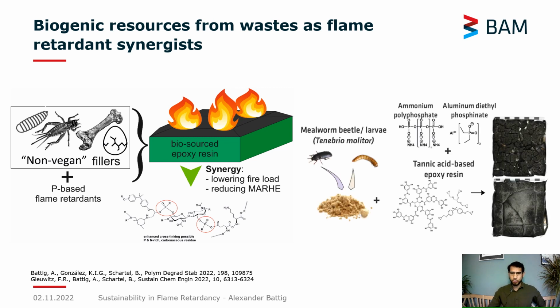And in another work, we investigated the yellow mealworm, so the mealworm beetle, but also the larva and also different compounds from it, fats, chitin, etc. We wanted to investigate which of these compounds interact with different types of flame retardants, one active in the condensed phase, one active in the gas phase. And we combined these into a tannic acid-based epoxy resin to make a more sustainable material and show as a proof of principle that specific compounds in these insects are actually creating a flame retardant effect on epoxy resins.